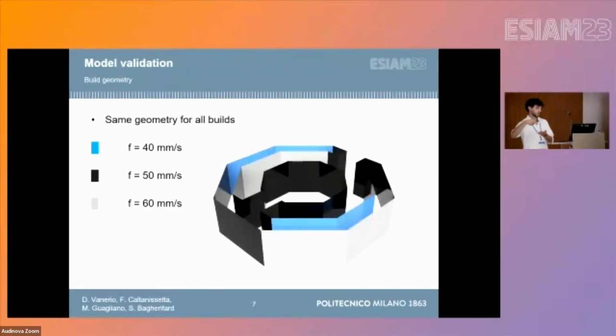The printing model is the one in the picture. For all tests, the same geometry was printed, just 3 different tests. And the different colored areas show you the different transverse speed of the robot. The light blue is 40 millimeters per second, the black one is 50, and the gray-white one is 60.